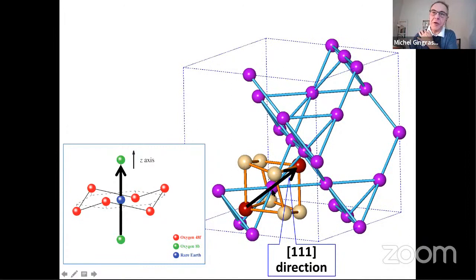Meaning that if you look at this site here, centered in the middle of the oxygen cage that I've marked, its Ising anisotropy, for example, goes from the center of this tetrahedron to the next one to the right. This corresponds to the 1-1-1 direction of the cubic lattice. These systems are cubic, and the direction that goes from this tetrahedron to this one is one of the four diagonals of the cube. So each of the sites on the tetrahedron has its own privileged anisotropy direction, which is one of the four diagonals of the main cube.